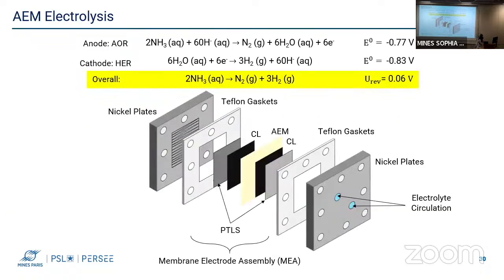In AEM ammonia electrolysis, the ammonia oxidation reaction takes place at the anode and the hydrogen evolution reaction takes place at the cathode. An AEM cell usually consists of polar plates with serpentine channels in order to allow the flow of the reactants, Teflon gaskets to control the compression of the electrodes, and an ion exchange membrane that allows the conduction of the hydroxide ions, which is sandwiched between two electrodes containing the catalyst layer. The combination of the membrane and the electrodes is called the membrane electrode assembly.